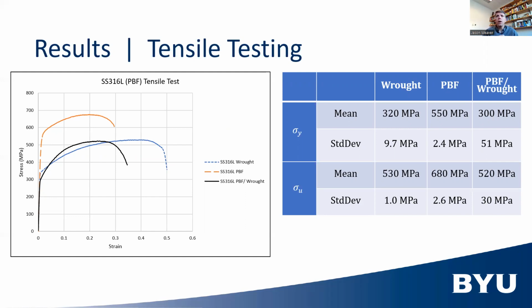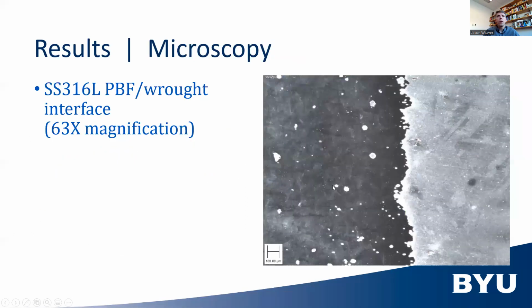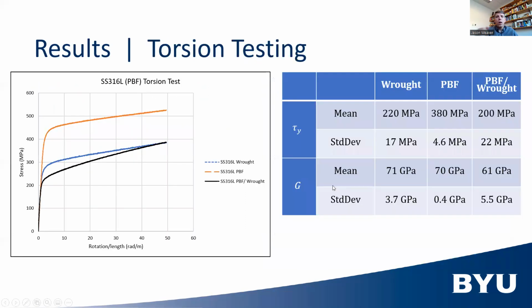And you can see we measured the yield strength and the ultimate tensile strength for each of these three varieties. Took a look at the mean and the standard deviation, all the normal measurements there. Same thing with our torsion testing. We can see the three different curves. We've got our shear yield strength and the shear modulus that we recorded.